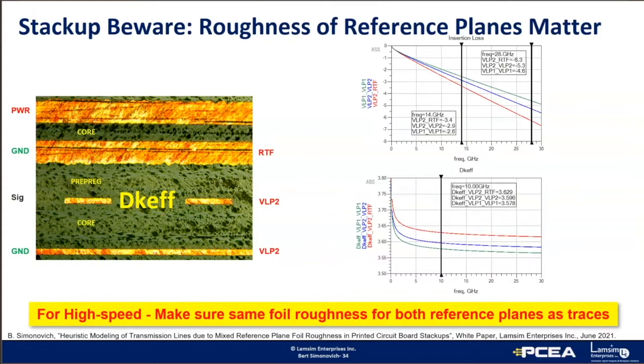In this example, with over 4 inches of trace, there's a delta of 0.8 dB at 14 gigahertz and 1.7 dB at 28 gigahertz. And since we're moving towards 112 gigabit per second for the next generation systems, that will cut into your loss budget and noise margin. And finally, you can see the effect of roughness on the effective Dk, which will ultimately affect your impedance.